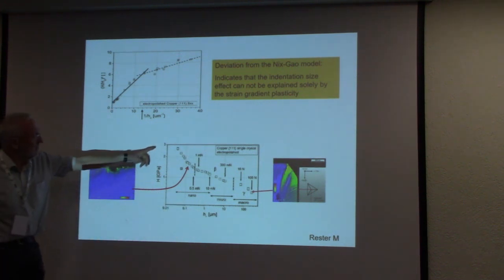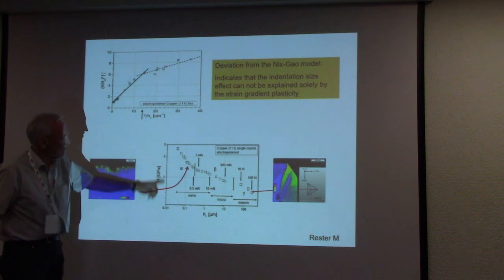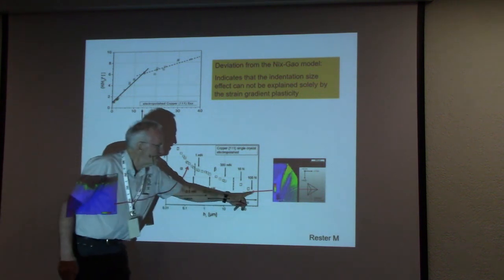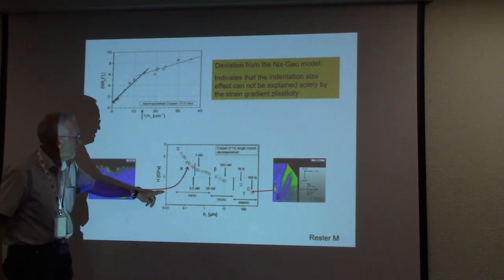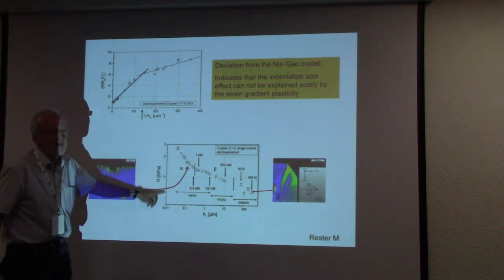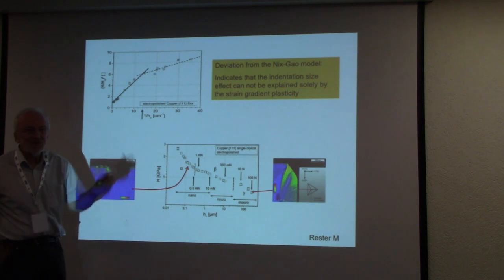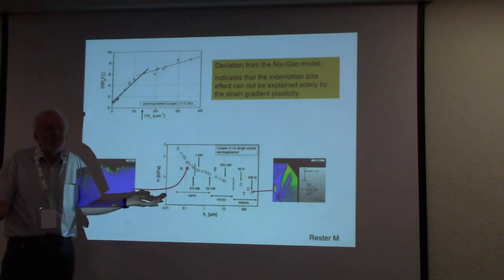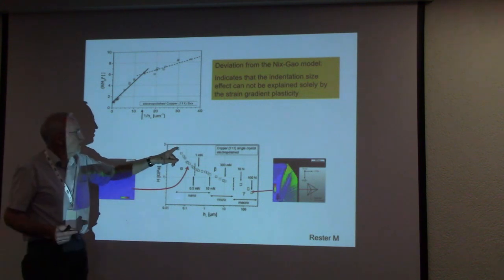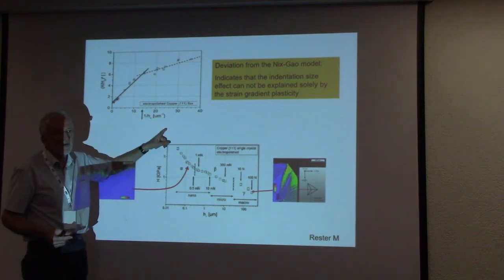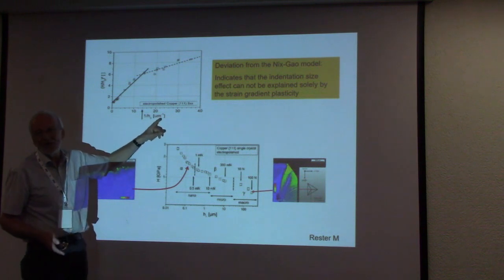And what you really see is that the hardness of your material here, when you go to the largest values, can be nearly 1 order of magnitude higher. It is exactly the same material. It's a perfect single crystal. And even if we would go to even finer, smaller crystals, we would come to higher values.